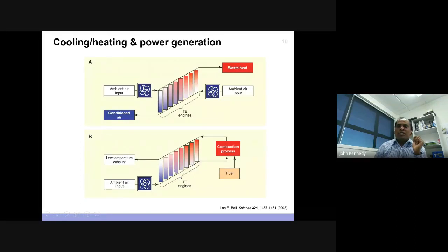So what we did is coat these films on the heat exchanger plates, because there's around 200, 300 degree temperature depending on where it is. If you have a junction there, it can absorb the heat, and we are able to demonstrate that you can generate a few volts, which can actually power even nearby electricity networks, like bulbs and buildings. And that's still better, because it comes from free waste heat.